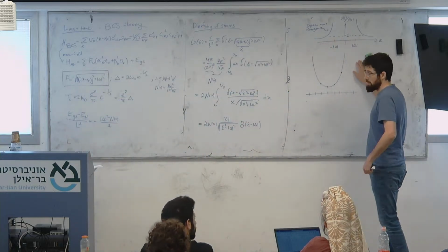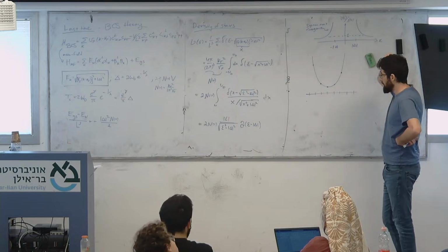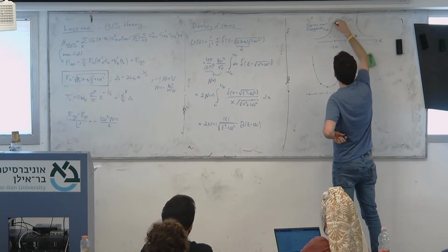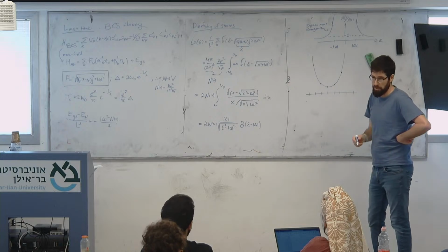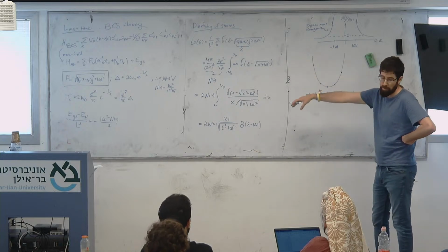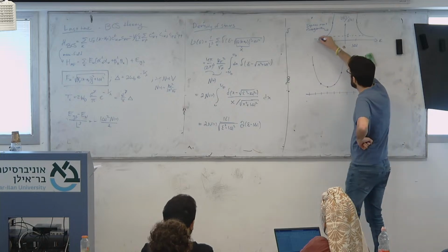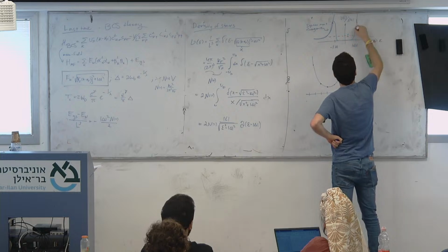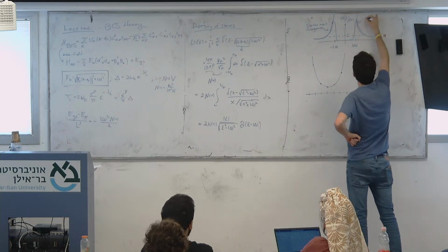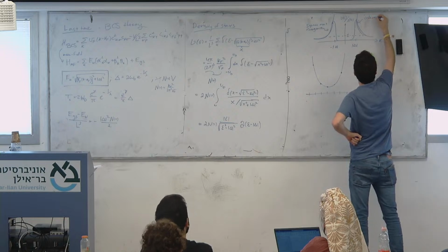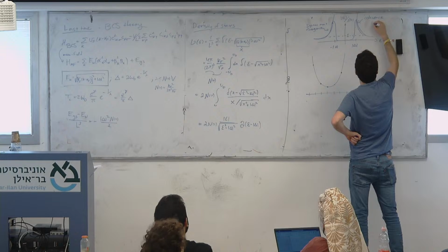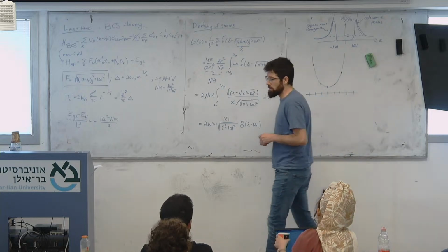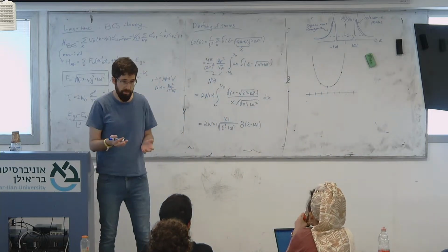The second thing is that this density of states can be measured. I should mention that it never looks ideal; it never really diverges. What really happens is, first of all, temperature smears it. We can do the same computation at a finite temperature, but I'm not going to do it now. What you get is that you kind of fill in the states, and these things are called coherence peaks. But there are other things that can also smear the coherence peaks, for example, disorder. You have disorder.